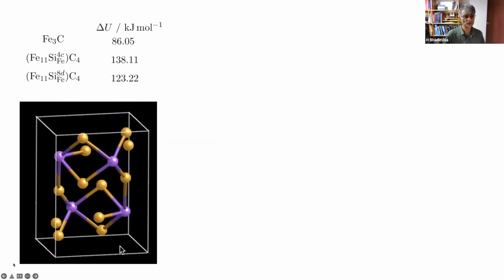You can take your unit cell of cementite, and there are two symmetry positions where you can substitute a silicon atom for an iron atom and calculate the change in energy. So this is pure cementite, and this is with a silicon atom substituted at a particular site, and you can see a massive increase in energy, and similarly at the other site relative to this. So you can then take these data and put them into a thermodynamic package, making gross approximations, because these calculations are done at 0 Kelvin and 0 pressure, really.